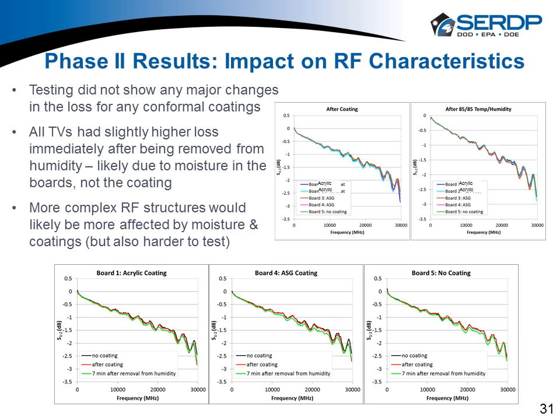We were surprised. We thought we'd see some changes, and we just didn't see any changes. It could be, too, that we need to use a different RF circuit that is more sensitive and does different things, or it could be that we need to expose it to maybe a different product use environment. But at least for the little we were able to do, we believe we were able to show some RF characteristics for both the ASG coating and just conventional coatings.